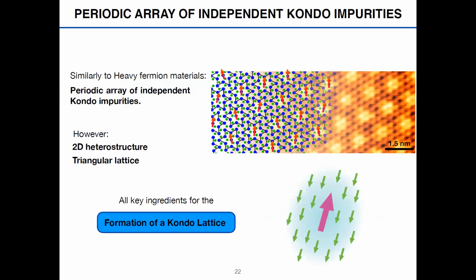Okay, so up to now, I'm going to do a brief summary. What we believe is happening here is that you have an unpaired electron at the center of each Star of David cluster. So the top is a Mott insulator, and below you have a metal. The electrons of this metal are screening this unpaired electron, and therefore when you do STS with the STM, a strong zero bias resonance appears.